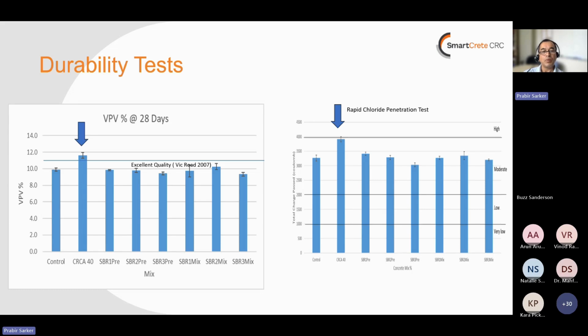Some other properties related to durability, which is the VPV, we can see again some improvement here with 1%. This is without treatment, and this is with treatment. Improvement means the VPV has decreased compared to the second graph to the third graph. This is again rapid chloride permeability. So without treatment and with treatment by 1% SBR latex, it showed some decrease in the RCPT and VPV.